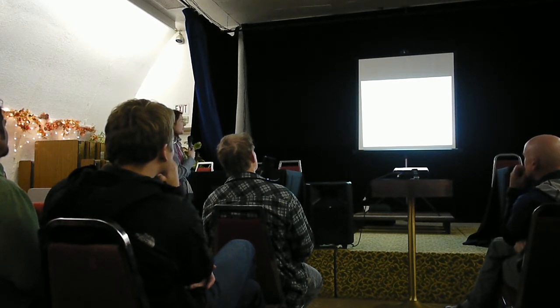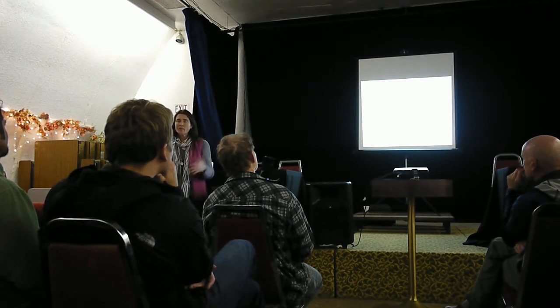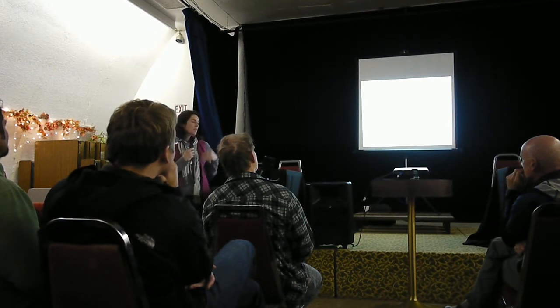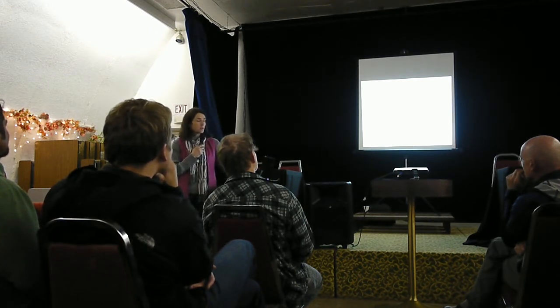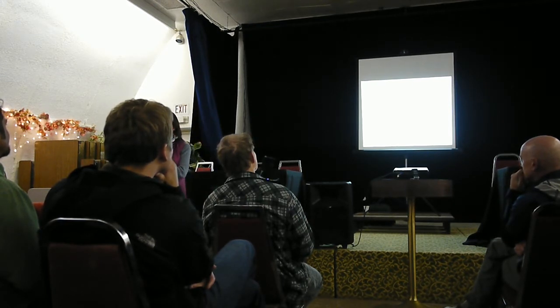What we're really talking about with these steels and atmospheric corrosion is that you have some thin film, and you got to wave your hands a lot when you talk about this. Some thin film with some salt. And then you have high humidity where you have a more dilute film, that would be the one on the left. You have low humidity where you're going to dry that out and you're going to get a really concentrated film, more corrosive. And at a certain point, it's going to be so dry that you're just going to have solids and you don't have to worry about corrosion at all.